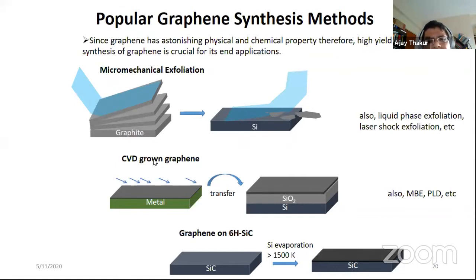So graphene primarily has three very popular methods of synthesizing. The first one is an exfoliation technique, and even there micromechanical exfoliation is most popular. This is the same technique which Geim and Novoselov used to make their first graphene samples. Here a scotch tape is used to peel off layers of carbon from a graphite sheet, and that is transferred onto a silicon substrate or a silicon dioxide over silicon substrate. And then one can make graphene using mechanical exfoliation. People have also developed other techniques, including liquid phase exfoliation and laser shock exfoliation, eventually to improve upon the yield and dimensions of the exfoliated samples.